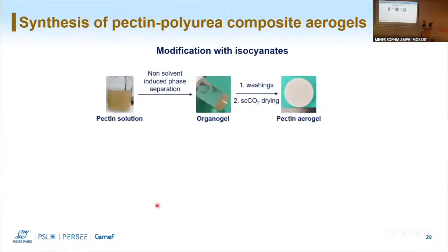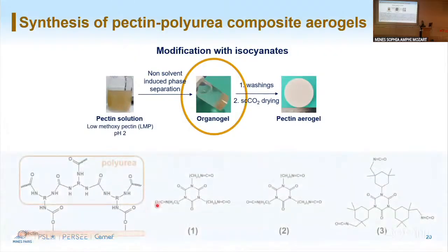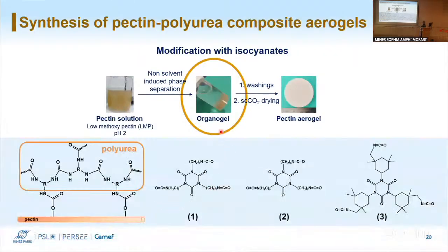Next, the last strategy to prevent aging was to prepare pectin polyurea composite aerogels. In that case, we did modification with isocyanates, and we worked with organogel again as a heterogeneous modification. For this work, we used the low methoxy pectin at pH 2. And here we see that we used 3 different triisocyanate molecules that can be grafted on the pectin fibrils and then polymerized to create a polyurea network.